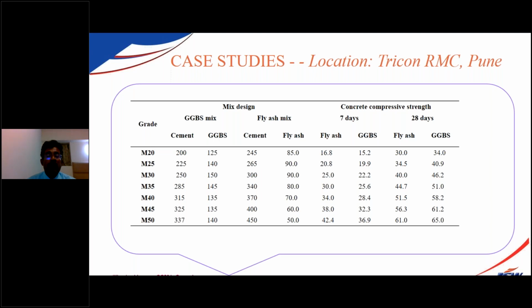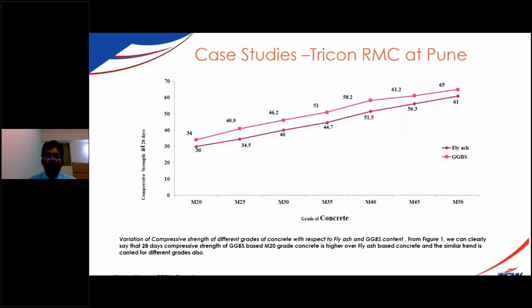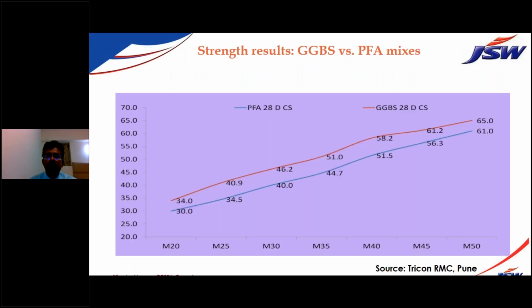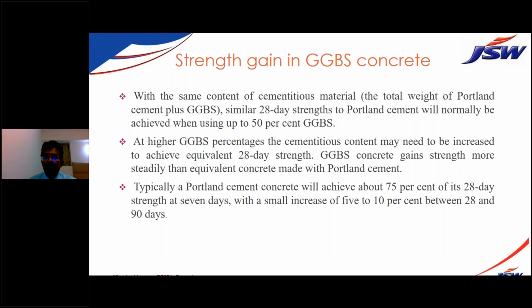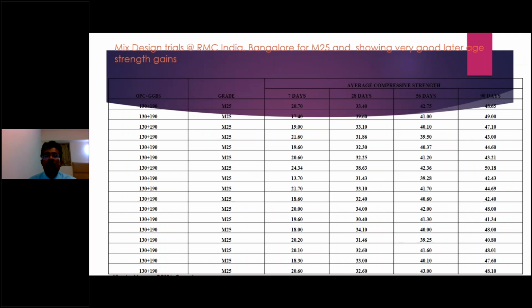At Tricon RMC in Pune, we did a comparison between fly ash mix and GGBS mix with various grades starting from M20 to M50. The GGBS mixes performed much better than the fly ash mixes. That is the beauty of the product. So many examples are there. Already discussed with you the advantages. This is one more mix design where we used 130 cement and 190 GGBS for an M25 grade of concrete. We can see various series of trials. When I was at RMC India, Bengaluru, we did these mixes. Even Kaushika is aware, also Mr. Shelly Fernandez is aware.